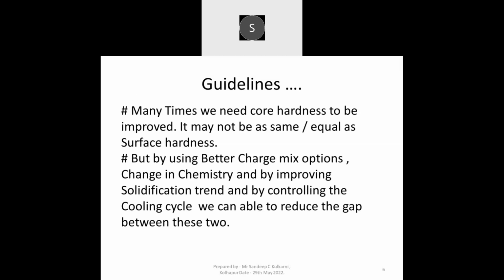Some guidelines to handle this situation. Many times we need core hardness to be improved. It may not be the same or equal to surface hardness because we have already seen that surface hardness will always be greater than the core hardness. But by using a better charge mix option, charge chemistry, by improving the solidification trend, and by controlling the cooling cycle, you can reduce the gap between these two. So we have to reduce the gap between the surface hardness and the core hardness, and for that we have to work on the charge mix, chemistry, solidification trend, and cooling rate as well.